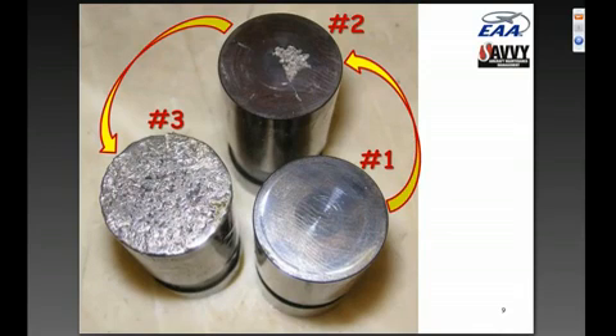This is a really neat picture. This is 3 lifters that were removed from a Continental engine, and they're shown in various stages of destruction. The first one looks pretty good unless you look at it very closely, and you can see that there are some scratches on the face of the lifter, probably because some foreign material got into the oil, sand or something like that. Maybe a bad oil filter, maybe a leak in the induction system. And once that surface was disrupted, the mechanical action starts to tear the surface apart.